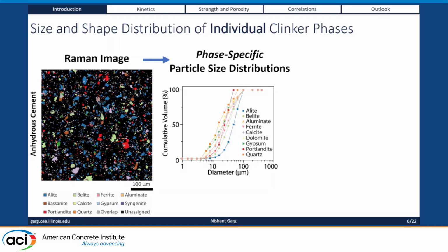And the interesting thing for me now, the next thing I'm thinking about is, we hear a lot about Type 1L cements and the variability and so on. It is possible, hypothetically, you could have two Type 1L cements with the same amount of limestone, 10% limestone, but depending on the grinding done at the different plants, the fineness of the limestone in one cement could be different from the other, and depending on the PSD curve, you could have different water demand and different strength. So that's something that would be very exciting to figure out. So if you want to collaborate on that, just let me know. I'm looking to get more cement samples.